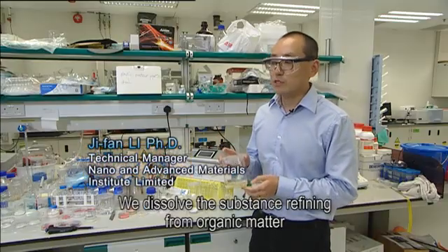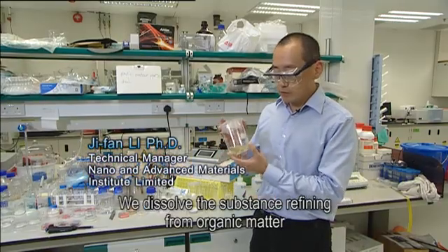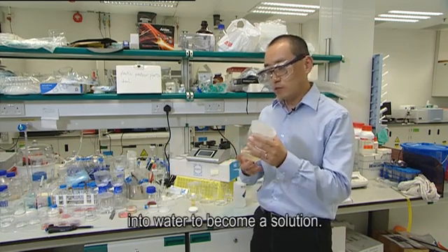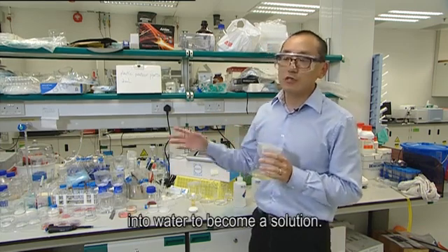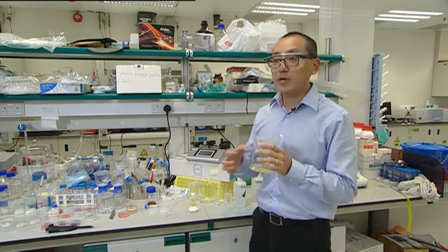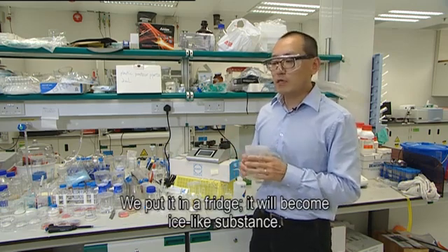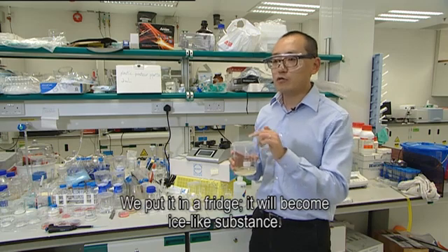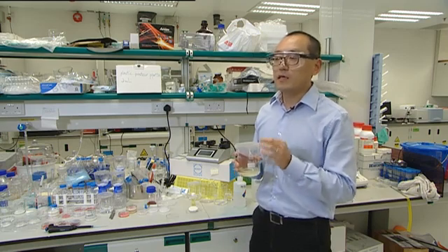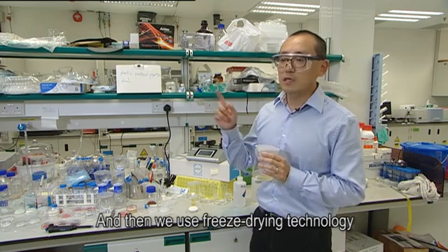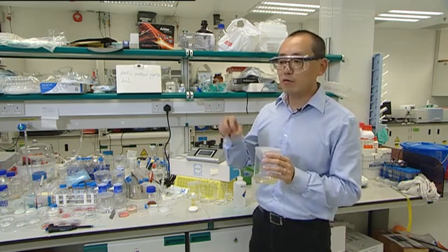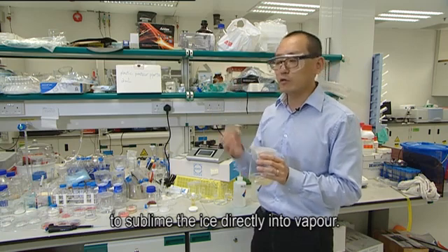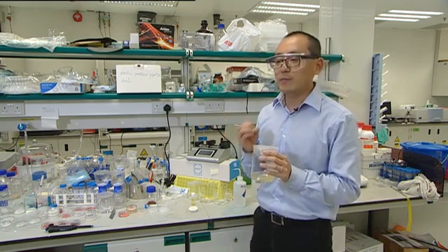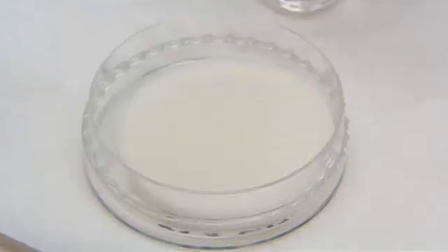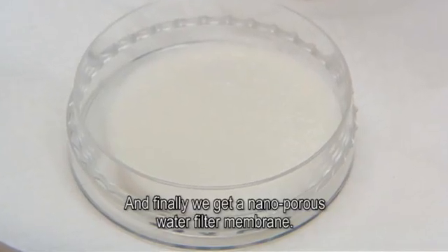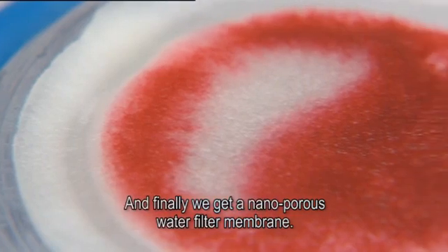We dissolve the substance, refined from organic matter, into water to become a solution. We put it in a fridge. It will become an ice-like substance. And then we use freeze-drying technology to sublime the ice directly to vapor. And finally, we get a nanoporous water filter membrane.